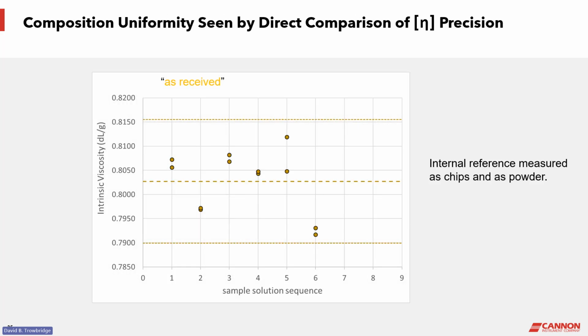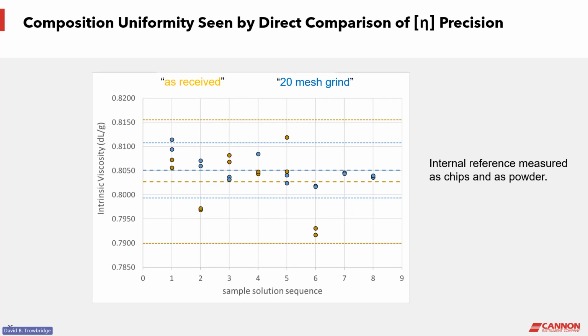They took chips as is, made a solution out of individual chips or several solutions, and ran the IVs. And this is the intrinsic viscosity results. We're looking at the spread here of the values. And then they took pellets and ground them up through a mesh into a powder, and measured the IVs, and you can see they're much tighter for these samples. So we've removed some heterogeneity that was present in the pellets themselves and formed a more homogeneous sampling from a powder generated by grinding through a mesh.